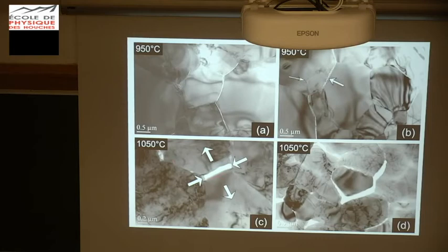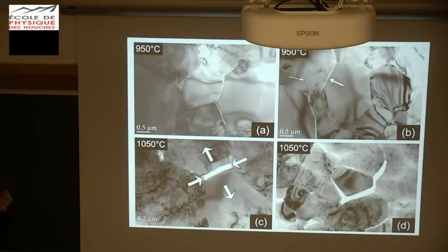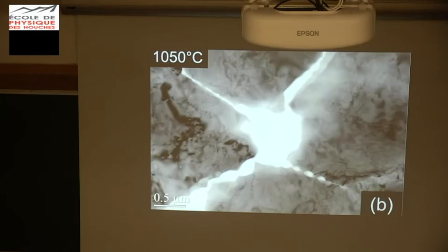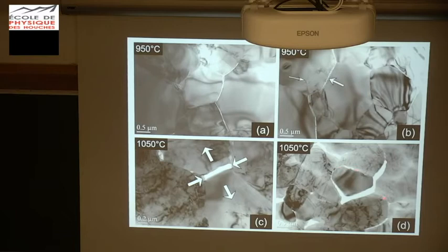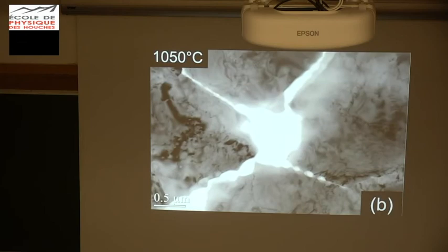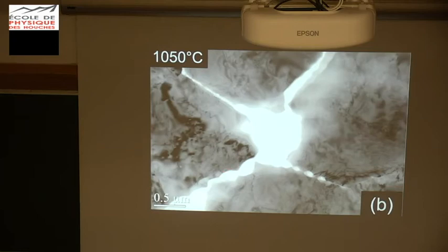At 1050°C, we have this very nice, almost geometrical opening, with some decohesion cells as well on the border. You can see it moved, but you cannot really pull it back together perfectly — you would have overlap of materials, which is also what the theory of grain boundary sliding predicts. It can be quite drastic with large openings. Some are still opening, and you also still have grain boundaries which remain tight. Remember, the confining pressure is 300 MPa and the bulk steady-state stress is well above the confining pressure.